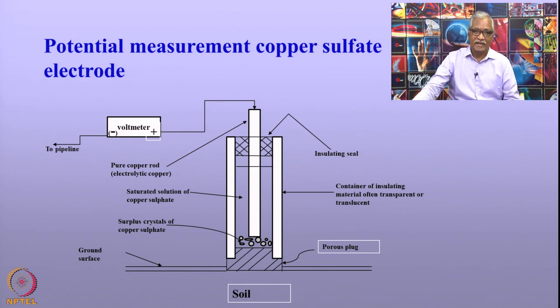In practice, there can be some kind of contamination, and the electrode potential can change. It is necessary to ensure that the potential of this reference electrode is as per the requirement. The only way that you can do it is to compare with another copper sulfate electrode or any other reference electrode which is not used. And if you are going to use another copper sulfate electrode, and the potential does not vary beyond 5 millivolt or 2 millivolt, then you are satisfied that this electrode is functioning. The reference electrode is connected to the pipeline through a voltmeter which measures the potential. The positive terminal of the voltmeter is connected to the reference electrode. The negative terminal is connected to the pipeline.